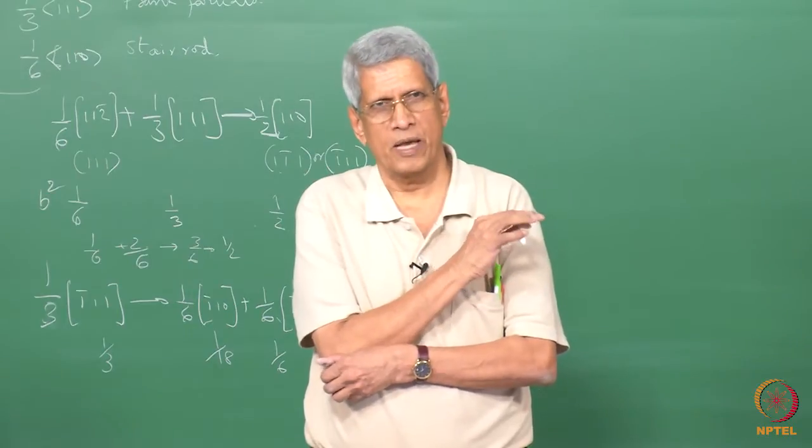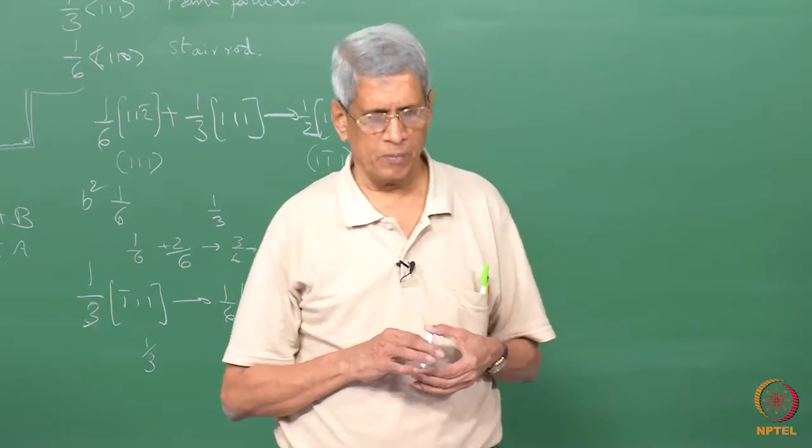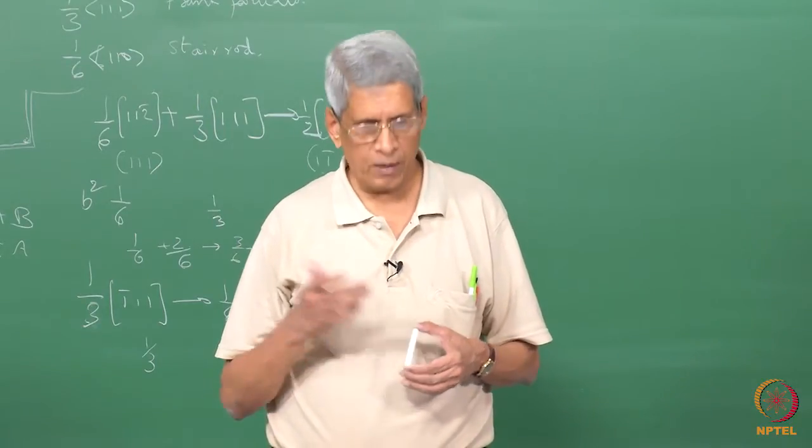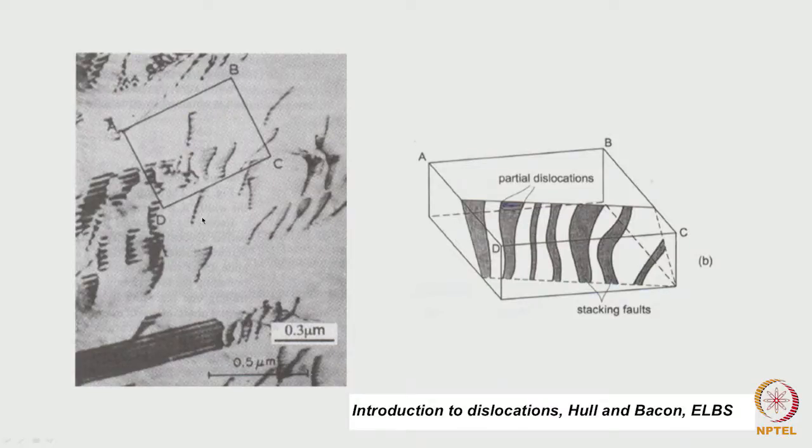in deformed samples. So this is just to give a flavor of how the faulted microstructure will look in an electron microscope. Here, if we look at it, all the dislocations are split into partials. So we can see the fringes corresponding to stacking faults. But at the end of it here we can see a partial, which is also visible. In this particular one, the partial is visible only on this side of it.